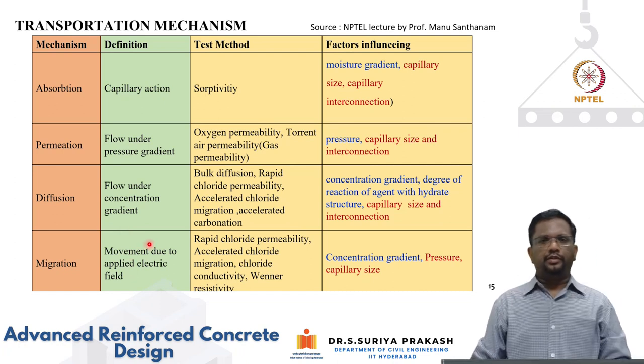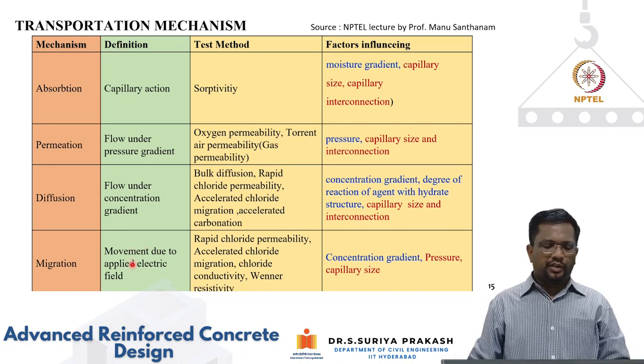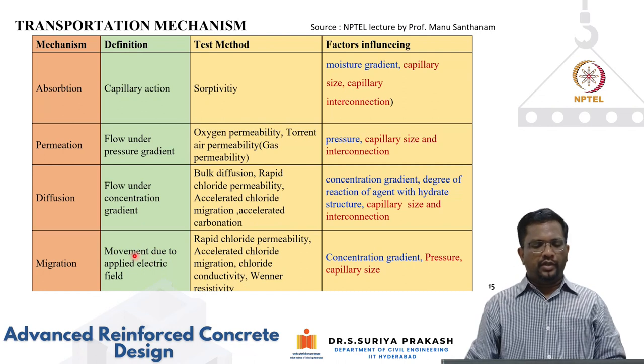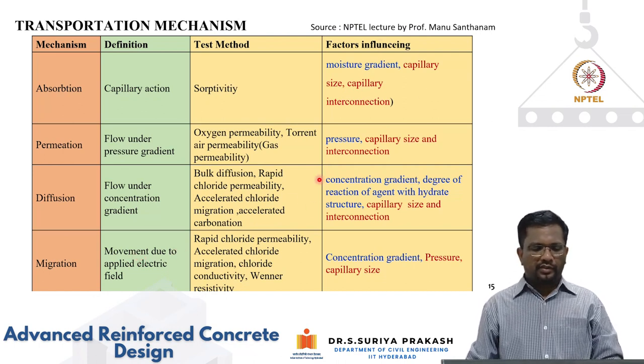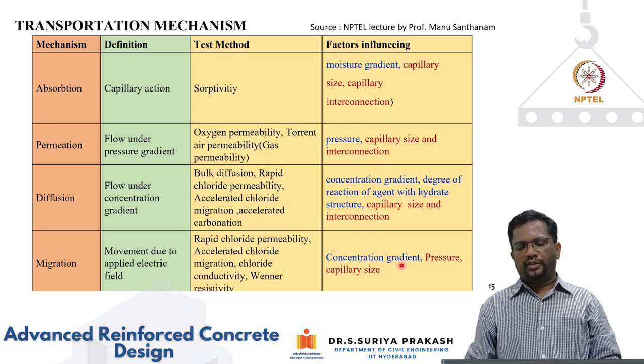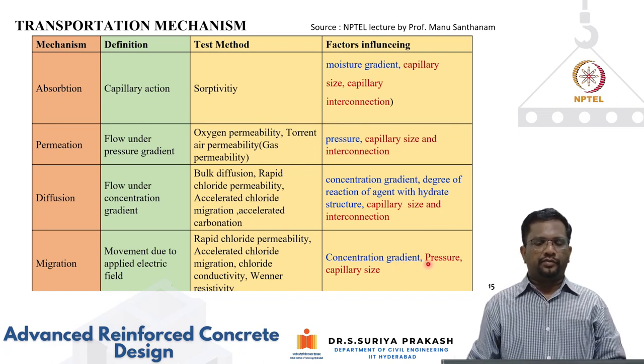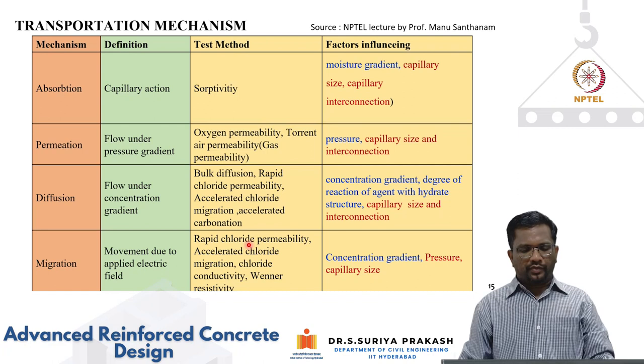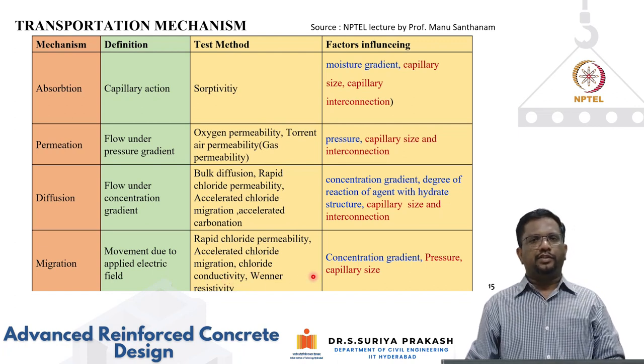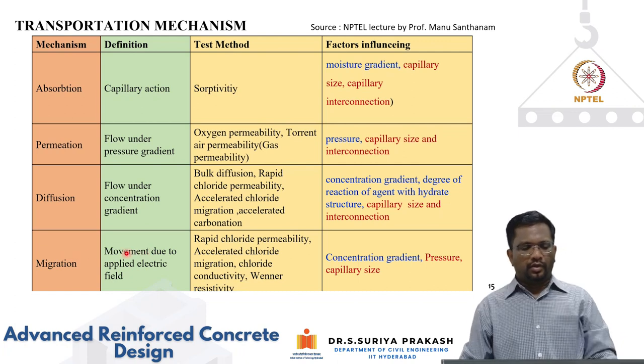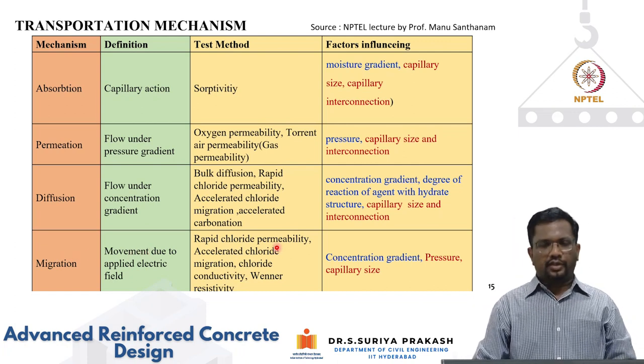The fourth mechanism is migration — the movement of ions due to an applied electric field. This is what is applied in the RCPT (Rapid Chloride Permeability Test). Factors affecting migration include concentration gradient, pressure difference, and capillary size. Test methods for migration include the rapid chloride permeability method, accelerated chloride migration method, chloride conductivity, and Wenner resistivity methods.